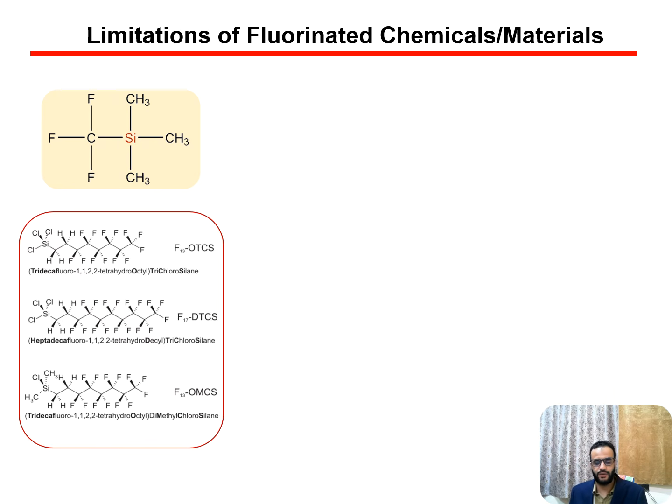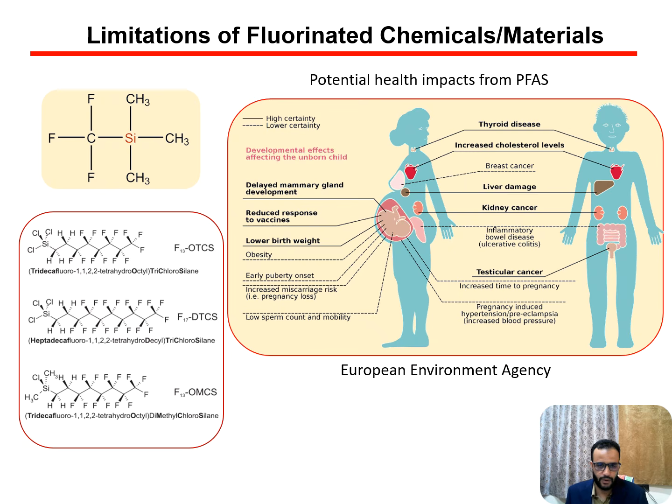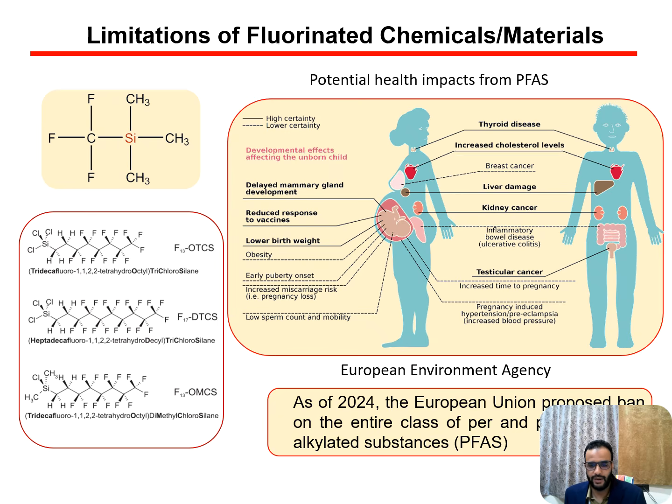However, in the broader context, the fabrication of super omniphobic surfaces needs the presence of fluorinated carbons, and it is well known that these fluorinated chemicals are environmentally unfriendly because they have a bioaccumulative nature and are responsible for various diseases in human life. Moreover, these fluorinated chemicals have been banned in different places over the years. So here our strategy is to design liquid repellent coatings without using the fluorinated chemicals or